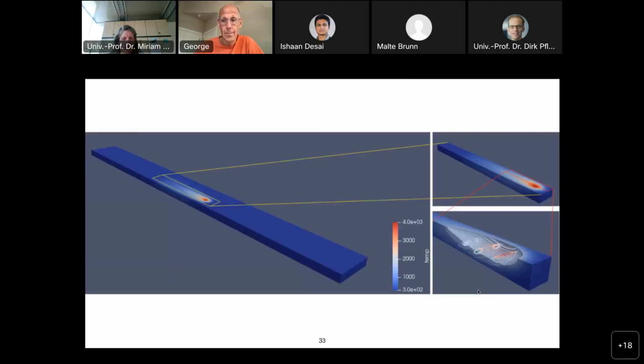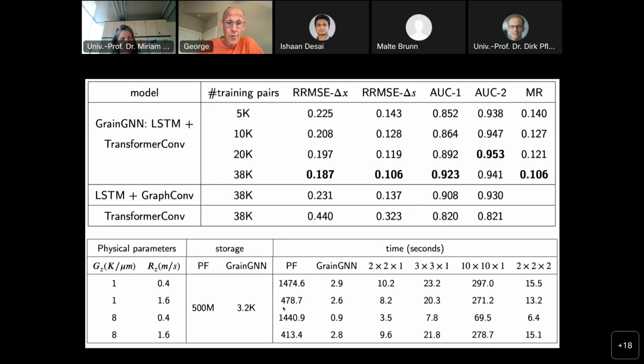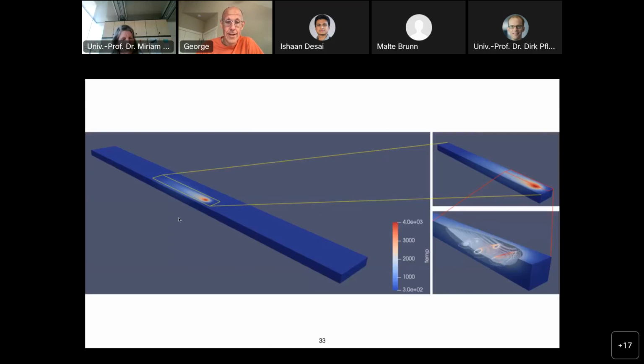So the savings will be tremendous, because in a real scenario, when we build a complicated part, this is for only one melt pool calculation. So for every melt pool, we have to do about, let's say, 100 random simulations in order to predict the quantities of interest in this melt pool, and then we have to do it for every location of the grain. So this is a scenario in which the reduced order model really pays off, because we're going to train for a variety of temperature conditions in one spot, and then we're going to be able to run the grain neural network for the whole build part.